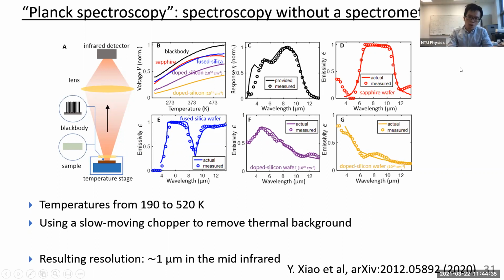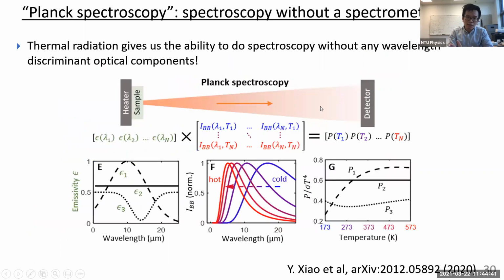So what are the constraints on the emissivity? I guess the emissivity captures everything, but there are some constraints on the types of emissivities that you can measure. Is the constraint basically this temperature thing? They don't have to be bosonic modes, they just all have to be at the same temperature? Yes. Certainly we assume that everything is at the same temperature, in thermodynamic equilibrium. If you don't assume that, then you can't define a single emissivity in the first place. And the other assumption we make when solving this inverse problem is that the emissivity has to be between 0 and 1, because that comes from thermodynamics.